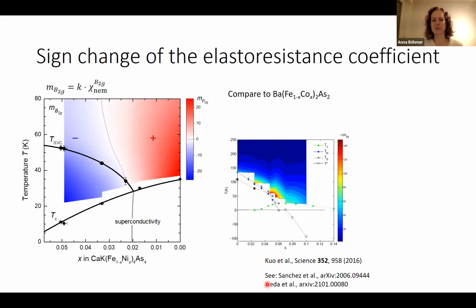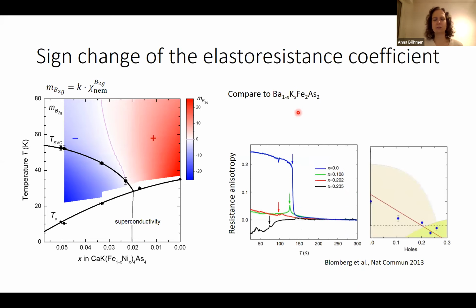And the influence of this prefactor was just recently discussed, well, just 10 minutes ago in the talk and these recent papers. So here we have a case, there's not only a magnitude change, there's a real sign change of the proportionality constant. And that's reminiscent of a result in the hole-doped 122 system. Here there's no elastoresistance data published to date, but there is a resistance anisotropy in strained or stressed samples. And the sign change was found there as well. So that seems to be related. And that comes from microscopic measurements of, well, scattering and Fermi surface changes, which was also explained here.